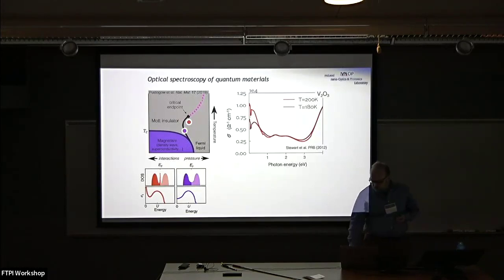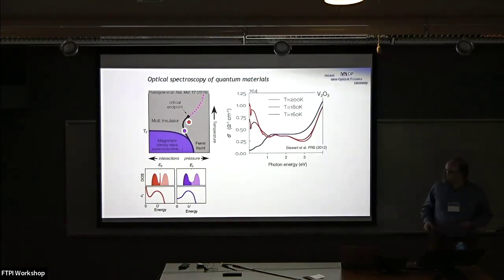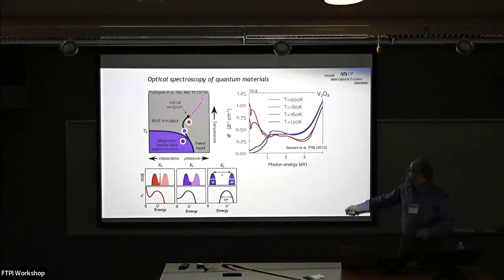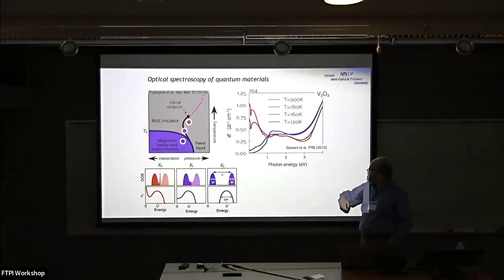Okay, so the coherence of quasi-particles drops. Eventually, of course, we open a gap if we go into the Mott insulating state, if it goes sufficiently down. In this case, into the ordered state, it happens to be an antiferromagnet, the V2O3. We have a clean gap. We have a signature in the optical conductivity. We have a gap in the optical conductivity, no more Drude response.